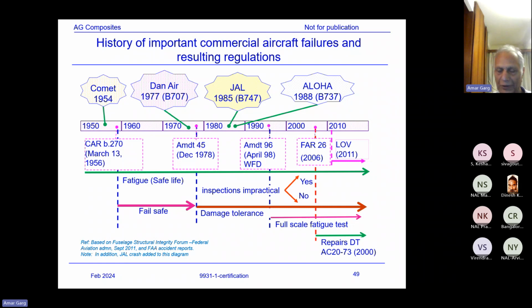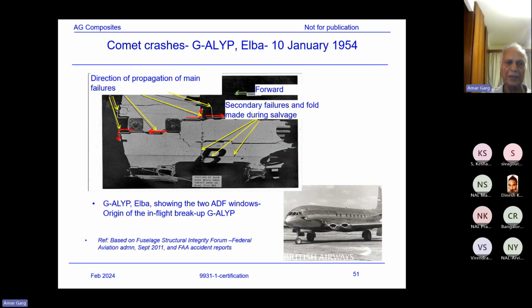the Comet aircraft, the first jet commercial transport aircraft, three Comets failed around the early 1950s, and that virtually finished the Comet industry. The major reason for the failures of the Comet aircraft, as I've said earlier, was the failure of the windows. Cracking initiated near the window corners. The design of the window was really not good because they had sharp corners, and nobody would design a window like this. They are normally elliptical so that they don't have stress concentration.